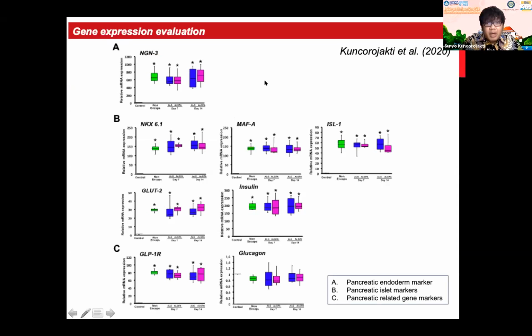The pancreatic markers were also observed in this study by using RT-qPCR to analyze the expression of pancreatic endoderm, pancreatic islet, and also pancreatic-related gene expression. As you can see, at day 7 and day 14 post-encapsulation, the alginate and also the alginate pluronic platforms could maintain the expression of pancreatic endoderm markers like NGN3, and also pancreatic islet markers NKX6.1, MAF-A, ISL-1, GLUT2, and also insulin, and also the pancreatic-related genes GLP-1R and also glucagon. Actually, this one is the marker of alpha cells.